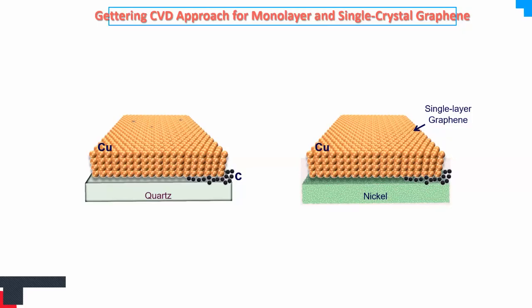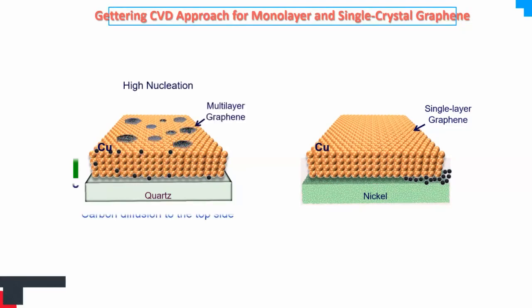So I will explain here a little bit more in schematics, kind of cartoons. In this first growth, we have copper on top of quartz. Some of the carbon from the backside can diffuse through and get to the top. Carbon often diffuses through copper because it has very, very little solubility. But at 1000 degrees Celsius, the solubility is a little bit higher as compared to room temperature.